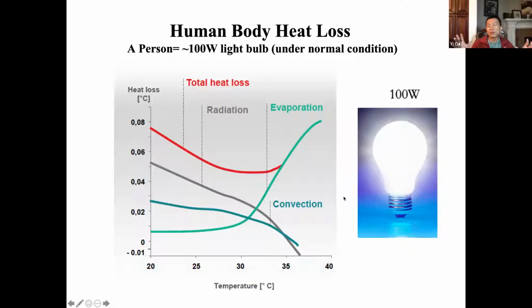The question becomes, instead of cooling and heating the building, can you cool and heat the individual? Then the thermal loss, as Jintu just introduced: one person is about 100 watts of heat under normal, non-exercising conditions, and radiation is one major mechanism for radiating out the heat. This heat loss has radiation, convection, and evaporation. Below 30 degrees Celsius ambient temperature, radiation can contribute a lot. Once you start to exercise and consume more energy, body temperature goes up, and evaporation will pick up. Convection is more static; it really depends on the local environment, whether you have airflow or not, and the porosity of your textile. So we focus on radiation in the indoor environment. That's one of the main heat loss mechanisms.